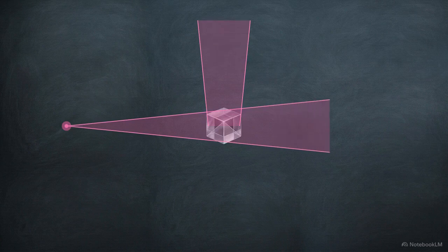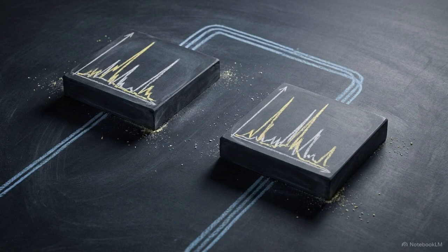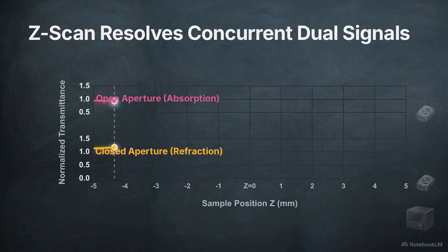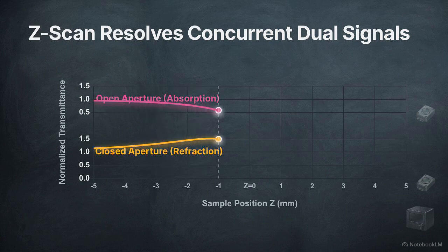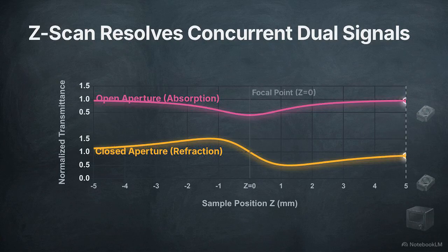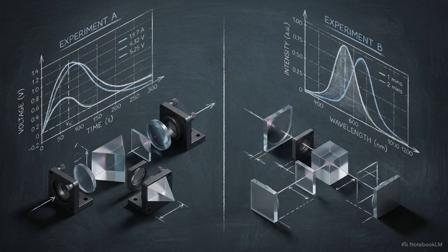After the light passes through the sample and diverges past the focus, it hits a beam splitter, dividing the transmitted pulse into two diagnostic paths. Splitting the post-focus beam allows the system to simultaneously measure two distinct photometric responses from a single physical pass of the sample. Acquiring both data streams concurrently during one continuous movement ensures the absorption and refraction data map to the exact same irradiance levels, eliminating the cross-calibration errors found in separate testing setups.